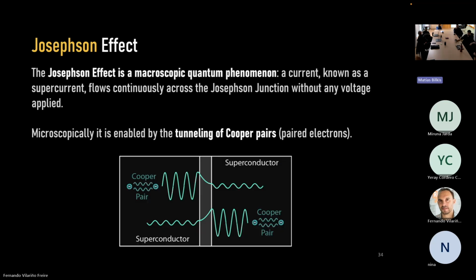For the quantum system, you instead employ this other thing, which is the Josephson effect. This is a macroscopic quantum phenomenon, which means that if you build a Josephson junction, you will have a supercurrent, as it's called, that continuously flows across the junction without any voltage applied. So it can flow eternally, basically. And microscopically, this is enabled by the tunneling of Cooper pairs, which, well, in a superconductor, you can look at BCS theory. This is another hour presentation, probably. But the electrons start to pair, they form Cooper pairs, now they behave like bosons, more or less, and they can tunnel through the insulating barrier in your Josephson junction, and this is the origin of the supercurrent.